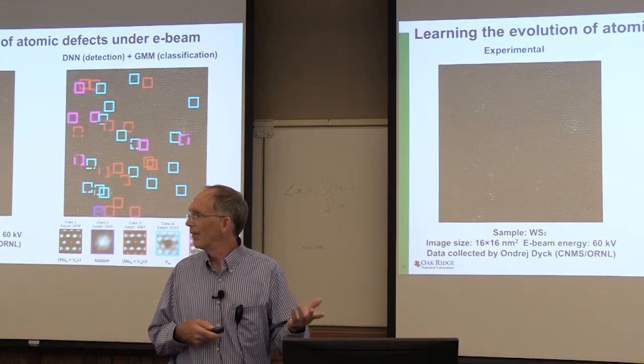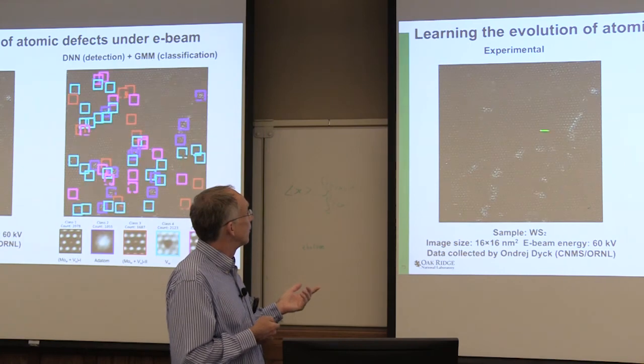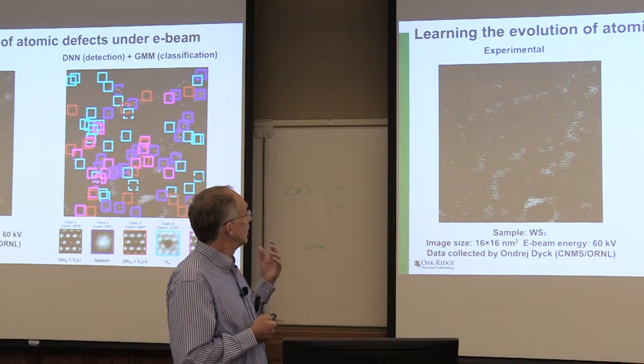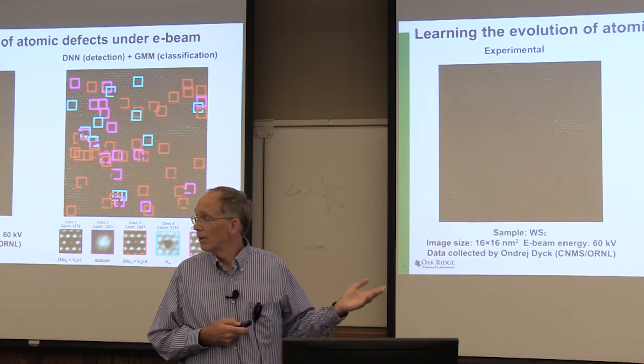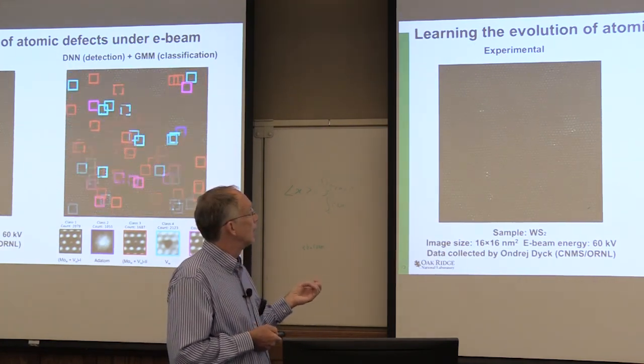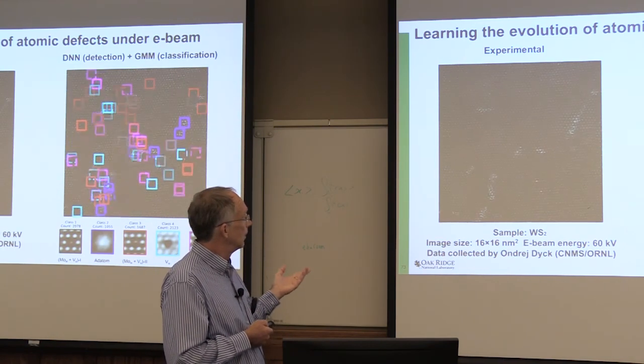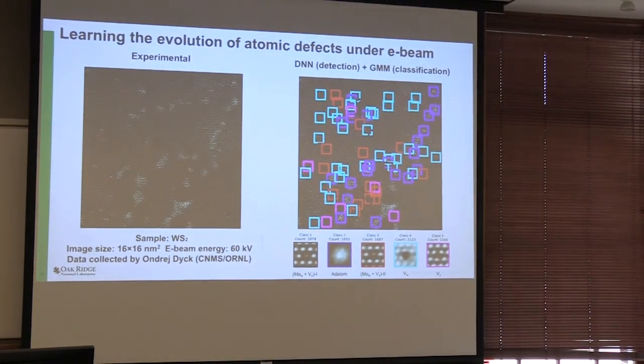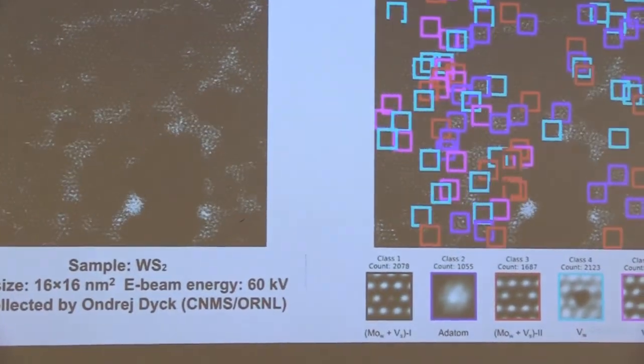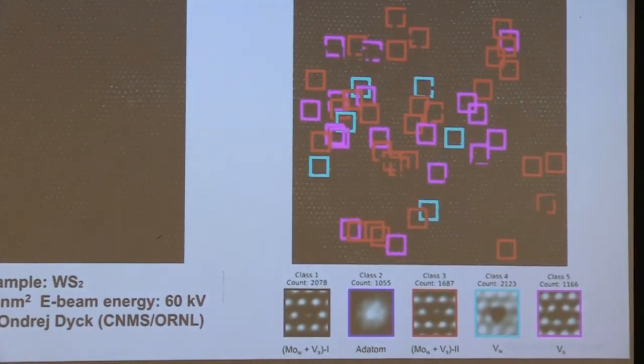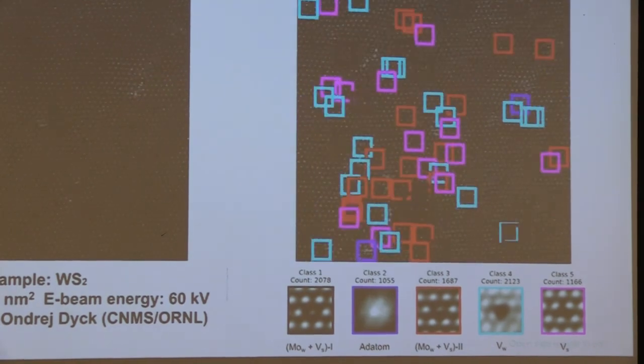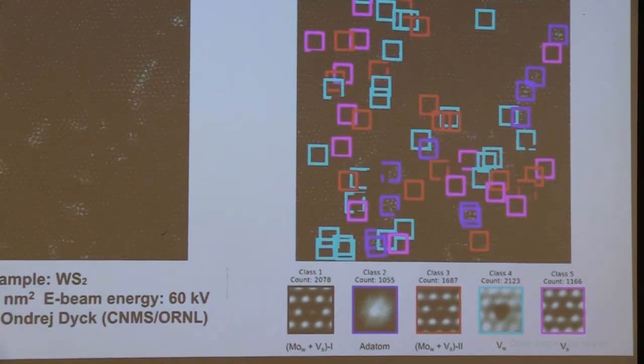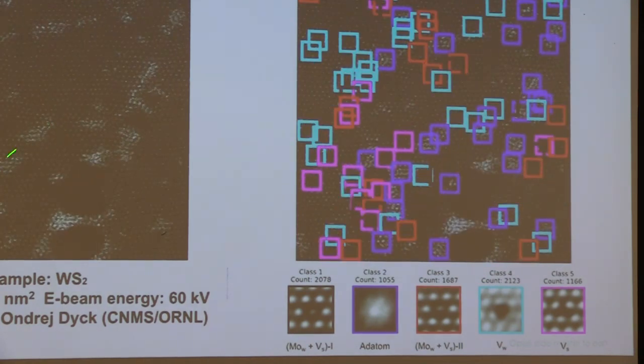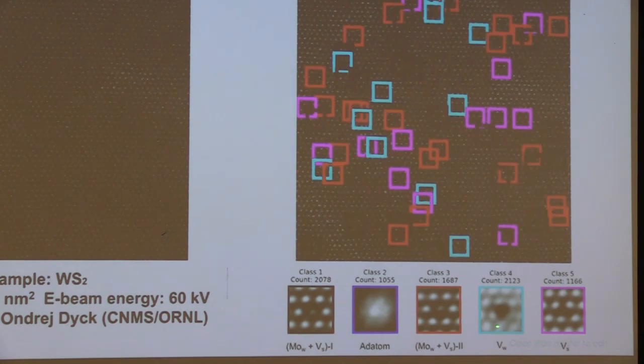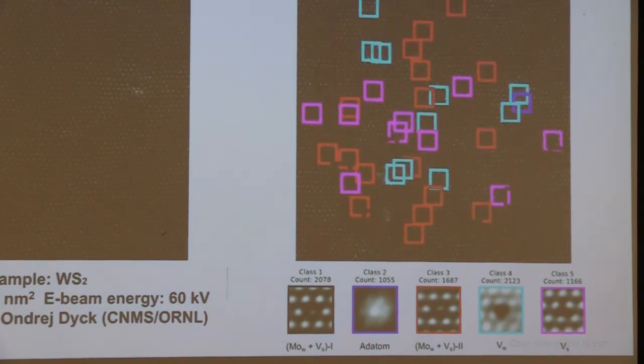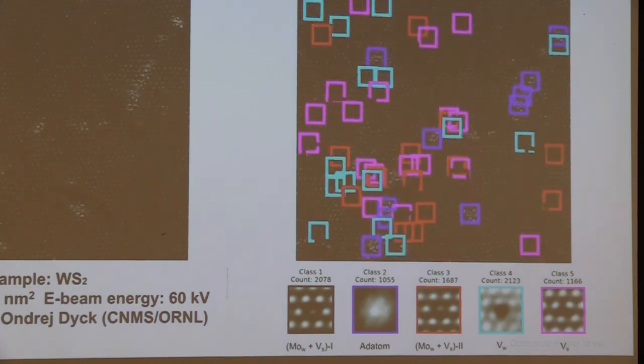Now, if it wasn't a lattice system, you'd have to have a different way of training this neural network. But for this case, we were able to just teach the neural network that there are certain types of defects that will occur. It automatically finds them. It always detects every defect that occurs. And then you can categorize these defects in different types. So this is molybdenum-doped tungsten disulfide, which is a hexagonal lattice system. And you find systems where there's a substitution of the tungsten with the molybdenum, which is here, which the molybdenum is not as bright as the tungsten, so it looks dimmer. You have an add atom, which is just a molybdenum or a tungsten sitting on top, which is this white stuff here. You also have cases where you have another type of situation that looks different than the first one, which is just a molybdenum substitution.